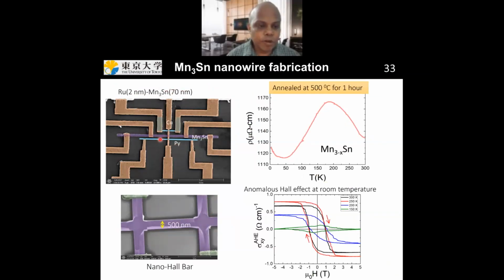In this case, you can see this is a non-local spin valve device, except in the middle, this purple line over here is a Mn3Sn nanowire. The width is 200 nanometers and the length is 11 micrometers. The most difficult part of this device fabrication is that it is very difficult to confirm this nanowire is Mn3Sn. To confirm this, we make a Hall bar just next to the device.